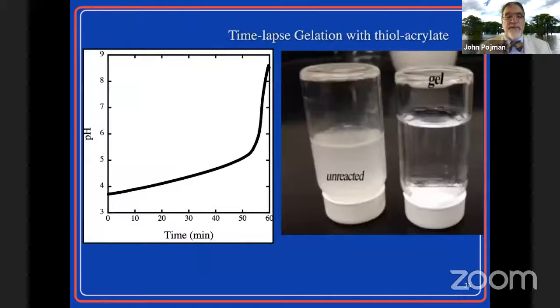And so these are the kind of experiments you can do. This is just showing the pH as a function of time. And this is now the initial solution. And then after the pH goes up, it's now a gel. And you can see it's a clear gel.